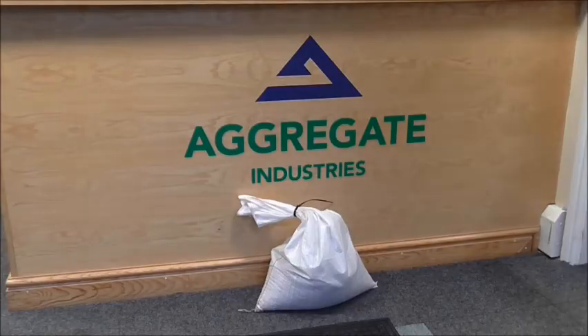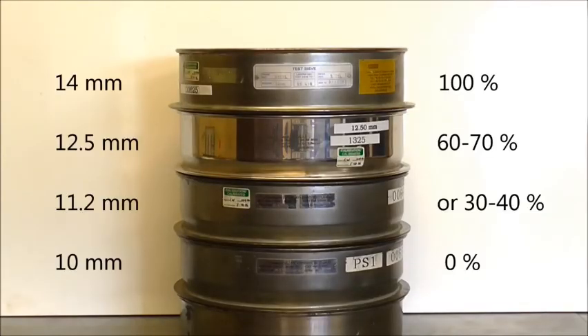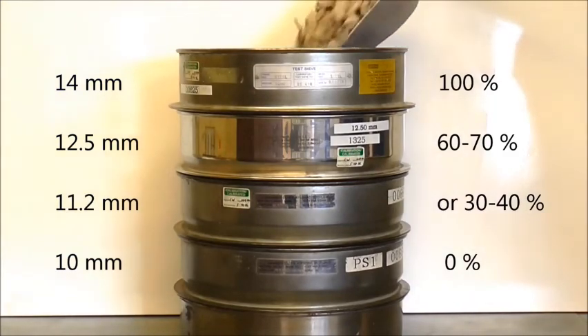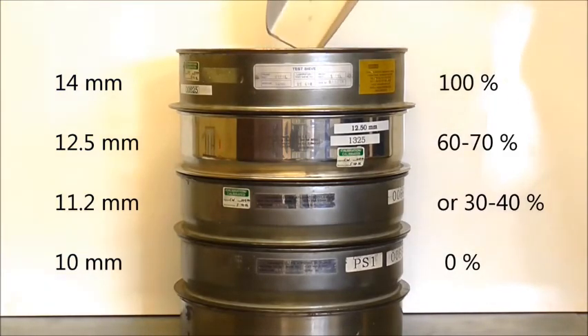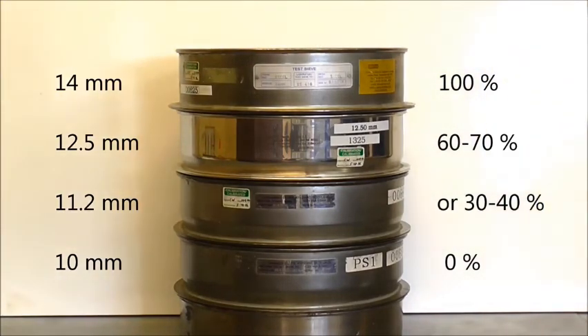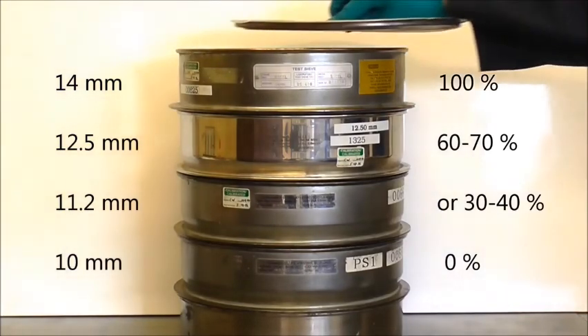The sample sent for testing must contain at least 15 kg in the 10 to 14 millimeter size range. Only material passing a 14 and retained on a 10 millimeter sieve is used. In addition to this, either 60 to 70% of this material must pass a 12.5 millimeter sieve, or 30 to 40% must pass an 11.2 millimeter sieve. The sample must be reduced to create two size fractions by using just one of the intermediate sieves.